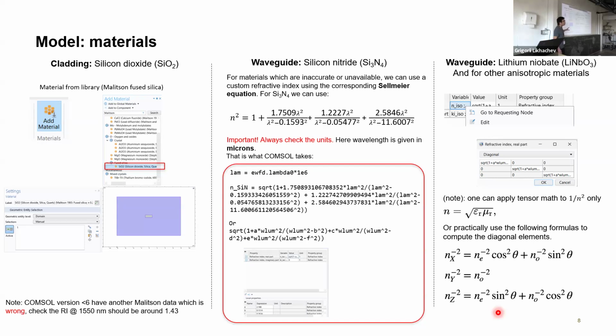But yeah, of course, you can have a bit non-stoichiometric silicon oxide. Usually silicon nitride is silicon rich, so that you have a higher refractive index than this. Yeah, and a kind of reference is what you get by oxidizing silicon. In nanofabrication we call it wet oxide or dry oxide. These things are usually pretty close to stoichiometric silicon oxide. So the Malitson data is mostly applicable.